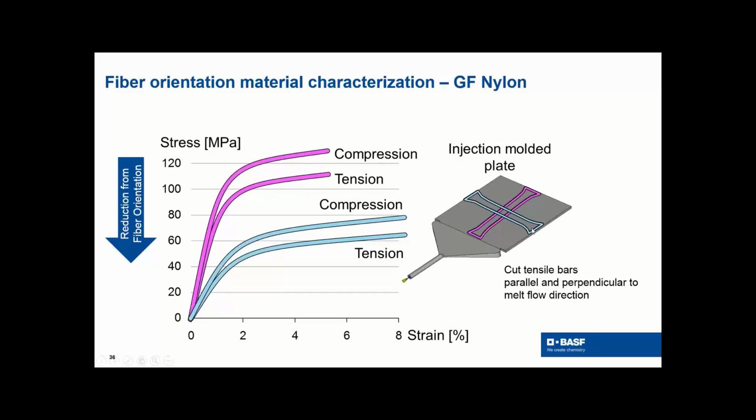It's going to be fairly strong. Now we look at the blue part, molded basically out of the same plaque or the following plaque. You molded 2 plaques, you cut this one out of the first one, you cut this one out of the second, and now this one here is only 70. So a huge difference. So in a complex part, you're going to have many different directions.